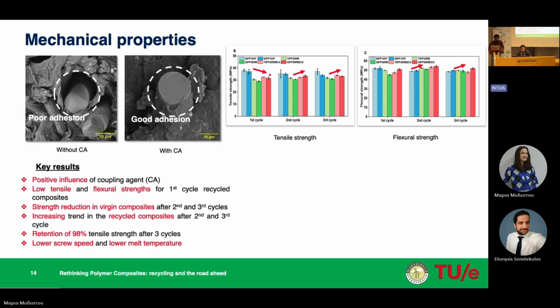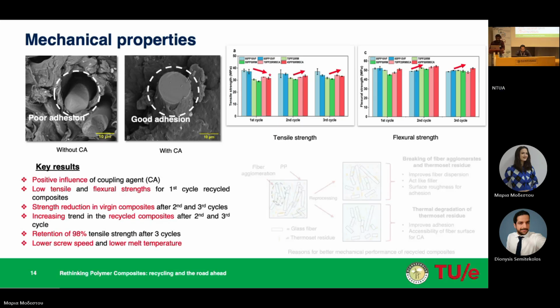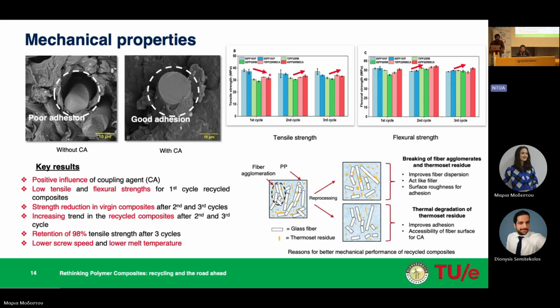strength enhancement. So there are quite a few reasons behind such an increase in the tensile and flexural properties of these materials. One of those reasons would be the processing parameters, such as lower screw speed or lower melt temperature, which will also affect the tensile and flexural properties of these materials. But we also have certain other possible reasons which will affect the enhancement of these properties.